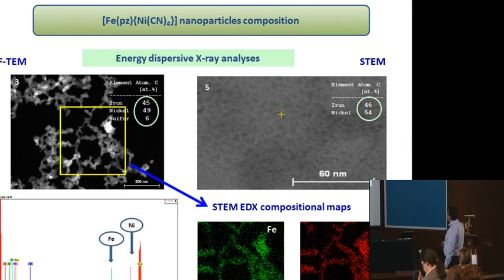Here is the characterization of the nanoparticles using dark field TEM pictures. If you analyze this part, we can find that we do have iron and nickel, which compose the clathrates. We have about 50-50, which is what we expect. We can also realize a map, confirming that we have iron and nickel at the same positions. This confirms again the composition of the two-dimensional system. Using this energy dispersive X-ray analysis, it's possible to probe only one small nanoparticle. So even for one particle of about 2 nanometers, it's possible to have this quantity. So even for the small nanoparticles, we have the good composition.